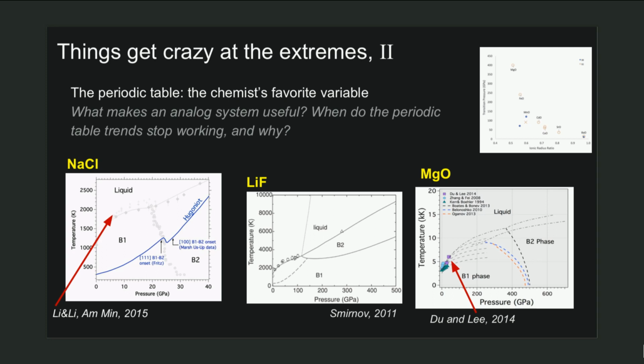And so a cool aspect of doing dynamic compression is that we can actually look more into these phase transitions. And so sodium chloride, for example, when you compress in a diamond cell, we know the phase diagram very, very well. But in dynamic compression, if you compress along the 1-1-1 direction, you transform at the same pressure as you do for diamond cell. But if you transform along the sides of the cube on the 1-0-0, you have to overdrive by a couple of GPa. And so this tells us that the energy pathway is more accessible when we compress along the 1-1-1 direction. And that's really cool. These mismatches tell us more about the nature of matter.